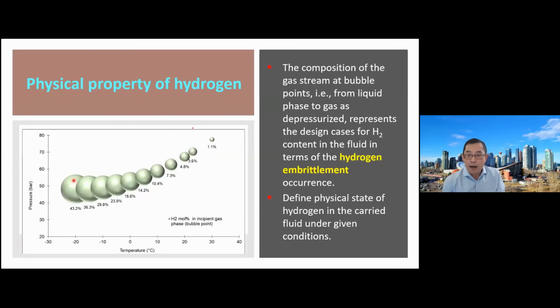The second one: for the given hydrogen pipelining conditions, in addition to the pressure and the temperature, we also need to pay attention to the composition of the gas fluid, especially for hydrogen and natural gas blends. From this graph, the top is liquid, the bottom is gas. For hydrogen embrittlement to happen, the source must be hydrogen gas. So if you want to evaluate whether a hydrogen embrittlement problem will happen, firstly you need to consider pressure, temperature, and composition to determine whether hydrogen gas is available in your system. This is the first condition you concern for the hydrogen embrittlement problem.